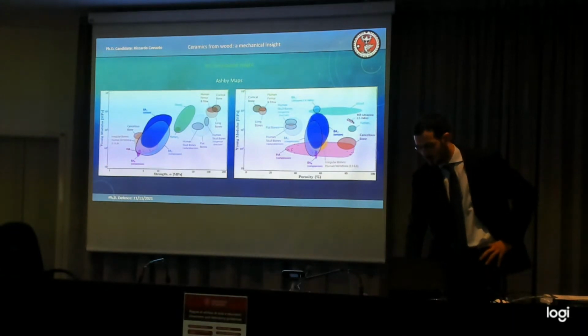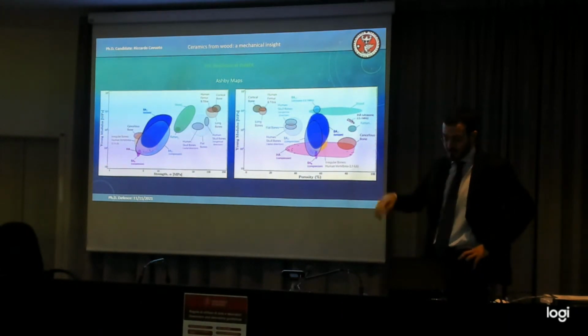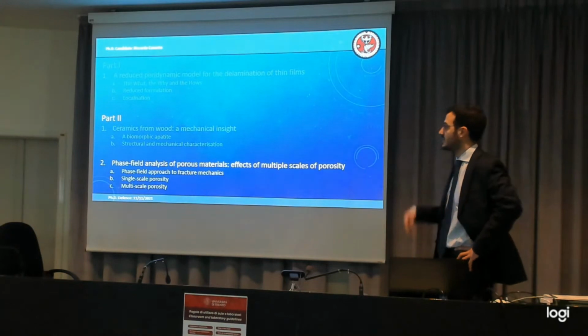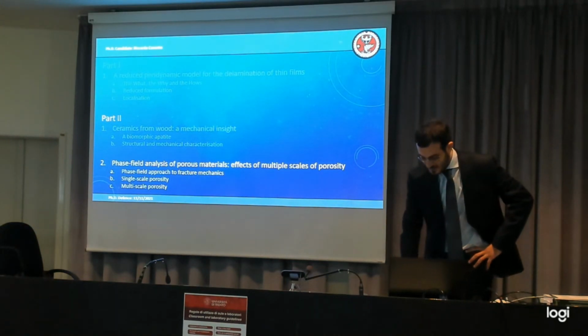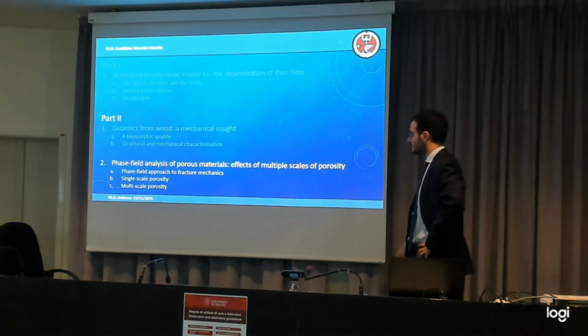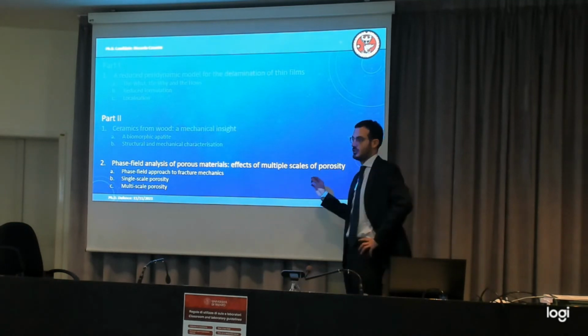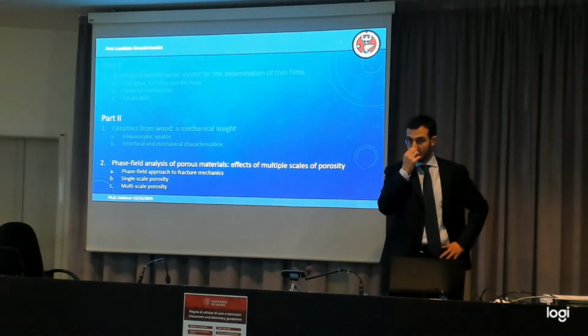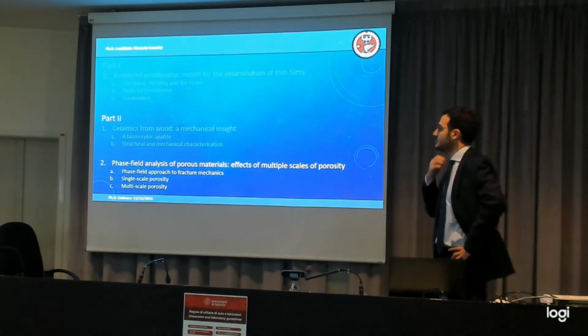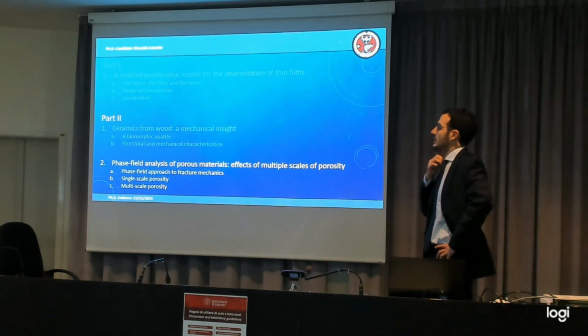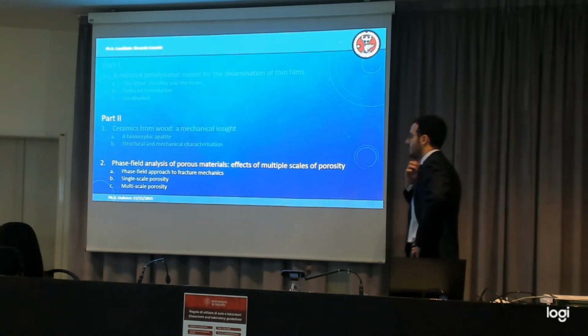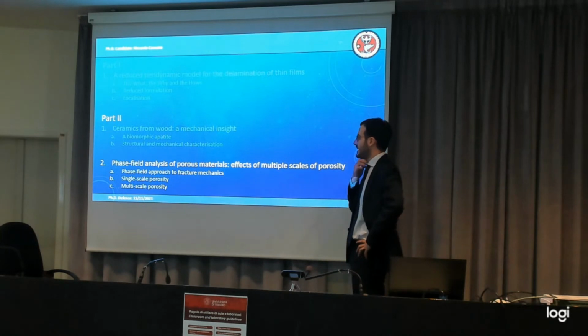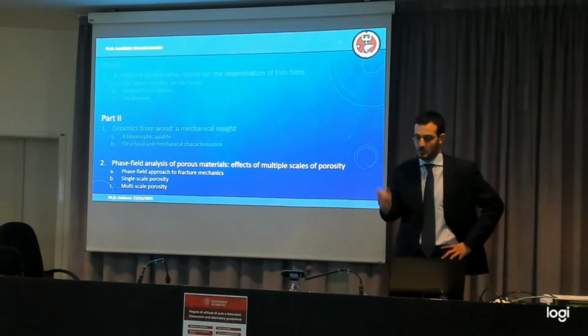I mean, also conduction. So cells need to penetrate the material as much as possible and transform it. So the nice and clean fracture propagating through the sample that we witnessed inspired our work on that aspect, and we wanted to analyze the effect of this multiple porosity on fracture patterns.